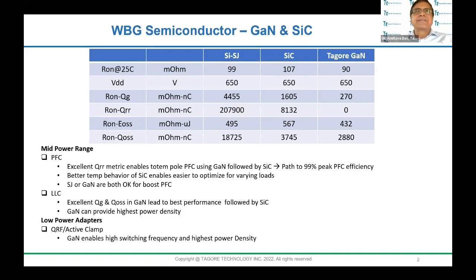In the LLC, which is part of the DC-DC, if you look at the various metrics that I listed above, you will see that the QG and QOSS in GaN are much better, and we feel that GaN can provide the best performance in the LLC, where you have soft switching, followed by silicon carbide. Also, if we can have magnetics which can support higher frequency, GaN will outshine all other technologies by providing higher power density.